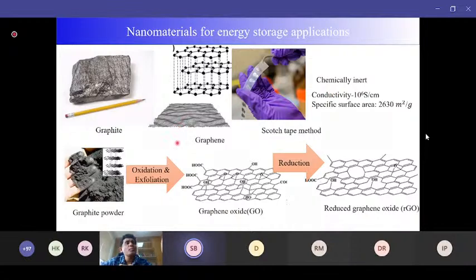Now, when it comes to energy storage devices, the scotch tape method is not an adequate method, because we need kilograms of this graphene. So for that, this is the most convenient strategy. It starts from graphite powder, which then undergoes oxidation. Because of the oxidation, some functional groups attach over each individual layer of the graphene. As a result of these functional groups, the distance between two layers increases, so their van der Waals interaction decreases. And if you just shake it or sonicate, they exfoliate into individual layers.